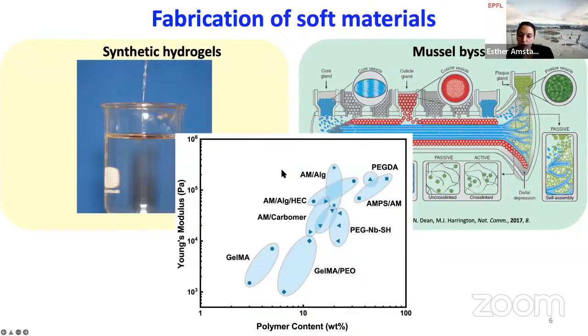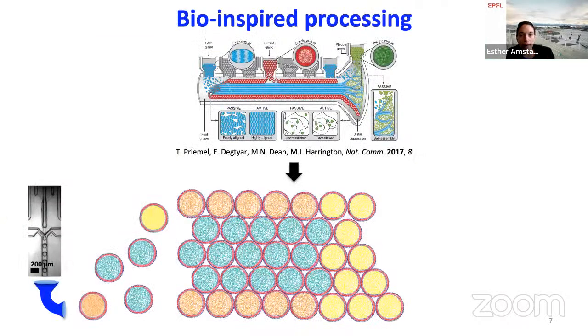But this is a summary of stiffnesses of 3D printed hydrogels. You see that they're all very soft. So we talk about 10 to 100 kilopascal. And if you remember, the mussel byssus is tens of megapascal. So there are orders of magnitude in stiffness that we just miss. And so this is, to a large extent, where my lab takes inspiration from to design more advanced soft materials that hopefully in the future can combine the mechanical properties and incorporate functionalities that natural materials actually do, but we just fail to do so with soft materials.